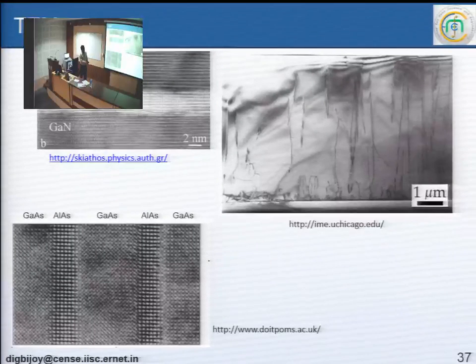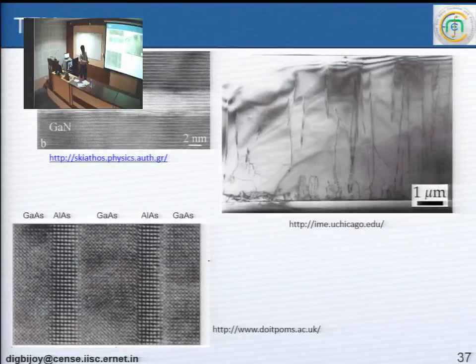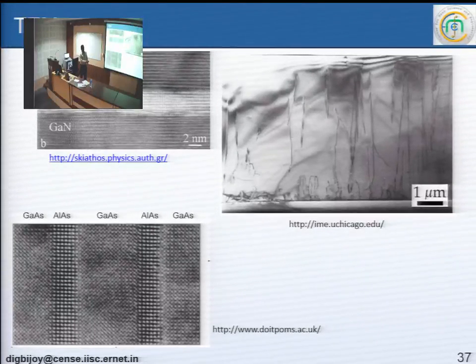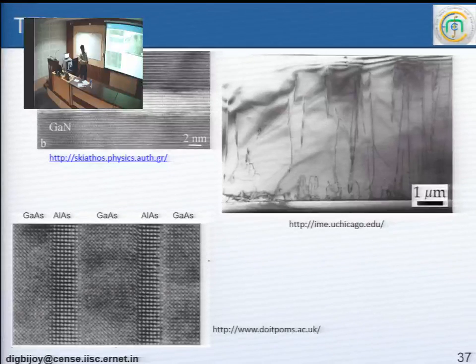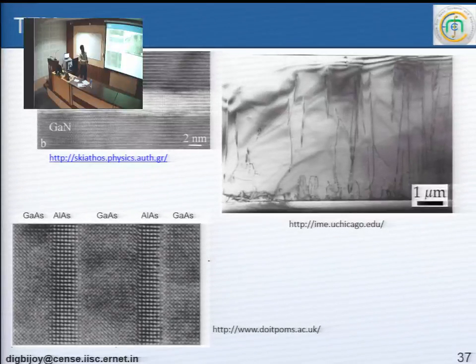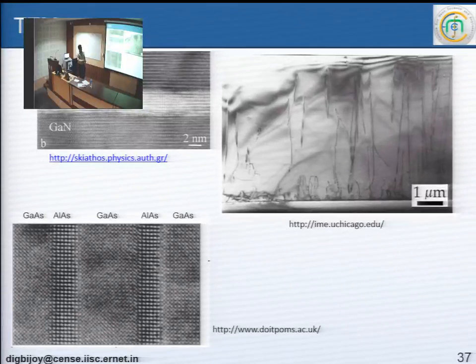So there's a lot of junk here, a lot of dislocations are here. But as they move up, they kind of annihilate, they destroy each other, and they reduce in number. That's how you want to go. You have a lot of dislocations at the interface here, and it reduces as you grow up. And this can be captured only by TEM, right? In a different imaging mode, it has captured what the dislocation looks like.